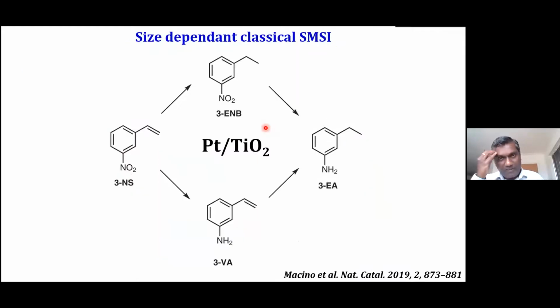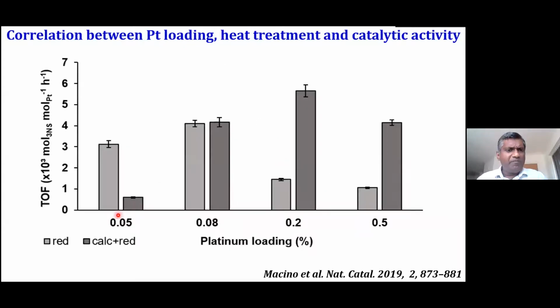So we contributed in this field a couple of years ago. For this, we used nitrostyrene hydrogenation, chemoselective hydrogenation of nitrostyrene. When we use a platinum catalyst, it selectively reduces the nitro group, and it doesn't reduce the carbon-carbon double bond. So this is the pathway it goes. We used platinum on titania as the catalyst, prepared by the impregnation method. We prepared different loadings of platinum on titania. One batch, we reduced the catalyst at 450 degrees C, and another batch, we calcined the catalyst at 450 and then reduced it.